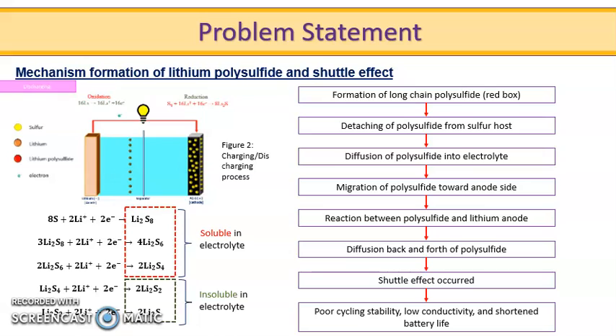Despite their advantages, lithium-sulfur batteries face numerous challenges, including highly soluble lithium polysulfide in the electrolyte that causes the shuttle effect. During the reduction process at the cathode, as you can see from the animated figure here, several reactions occur. The long chain lithium polysulfide, as indicated by the red box, will form, and then it will detach from the sulfur cathode here and diffuse into the electrolyte, and then migrate to the anode side with lithium at the anode. The diffusion of lithium polysulfide back and forth between anode and cathode produces the shuttle effect. This results in poor cyclic stability, low conductivity, and shortened battery life.